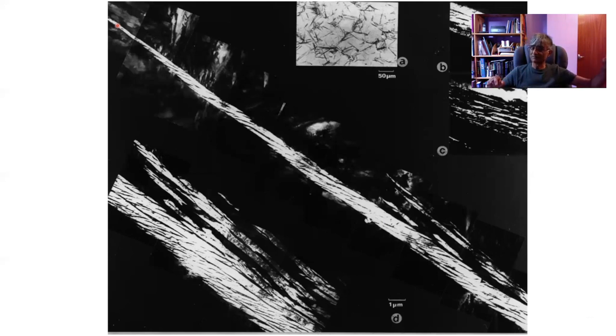which leads to a remarkable refinement of structure, because if this was martensite, it would form as a single coarse plate, okay? So there is no thermomechanical processing method which can give you a grain size which is a quarter of a micrometer, because for a thin plate shape, the mean free slip distance is approximately twice the thickness, okay? So this is a huge refinement of the structure. And grain refinement is one of the few methods where you can increase strength and toughness at the same time. Okay, so these little platelets are lens-shaped with sharp tips, as you can see here, and they are very fine. And we can see the shape deformation both due to the individual platelet and due to the overall collection of platelets in a sheaf of platelets.